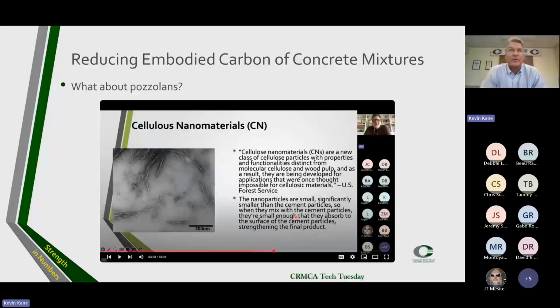Cellulose nanomaterials. I wish John Belkowitz was on the line. Nanometers. What's the difference between a nanometer and a micron? I believe a nanometer is 1/1000th of a micron. A cement particle is 30 microns. Look at how small they're talking here on these nanoparticles. Little teeny tiny particles that get into the cement particles and increase the hydration products. Really neat science.